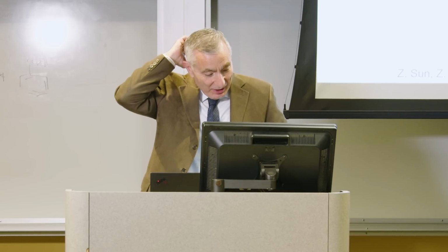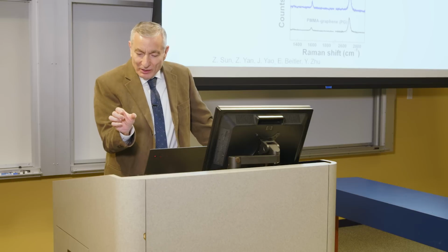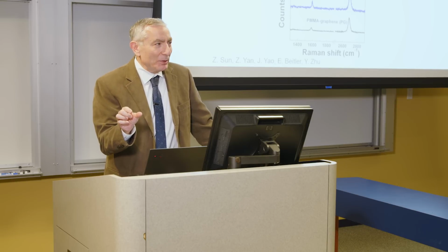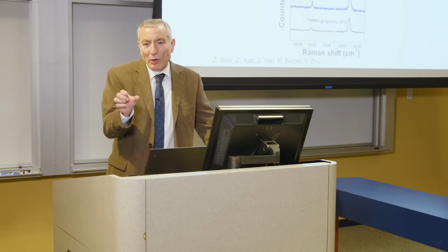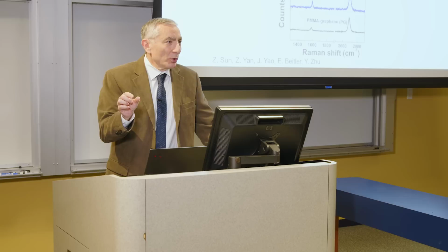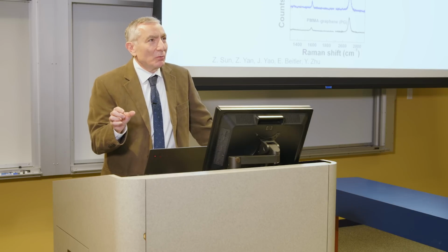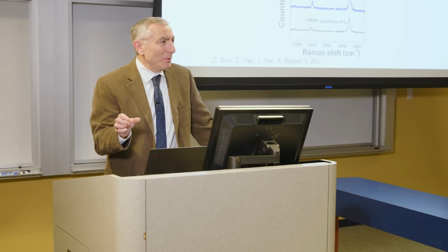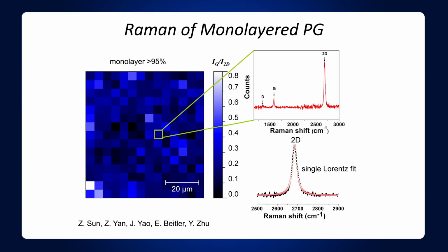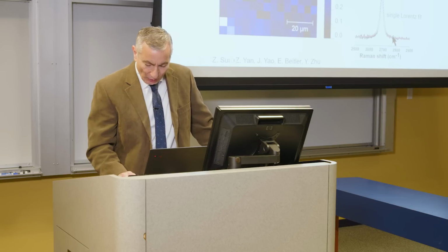I'm talking about like it was a little piece of graphene, tiny little piece of graphene was like $250. And we're talking about something that weighs, like about 10 nanograms. I mean, like nothing. And we characterized it, and this is what really good graphene should look like. It should have this is the graphitic band, this is the 2D band, and the 2D band fits to a single Lorentzian fit, and you scan it over a whole area.